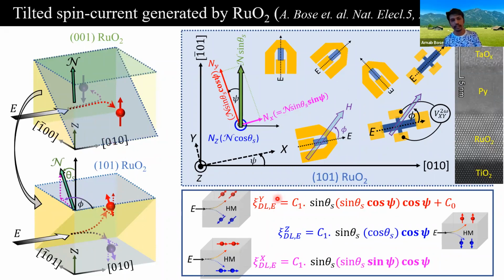Now, the third projection is for the direction of the spin flow. Again, the theory predicts that when we run current along this direction, 0, 1, 0, then we'll have pure spin current transverse to this, which is minus 1, 0, 0. However, we are not measuring spin current in this direction.